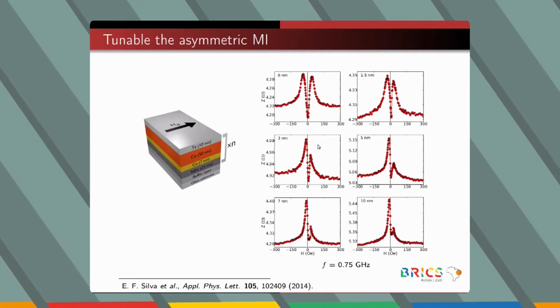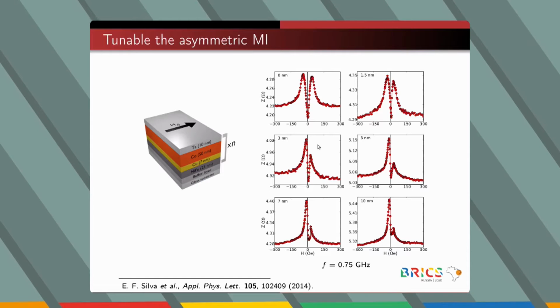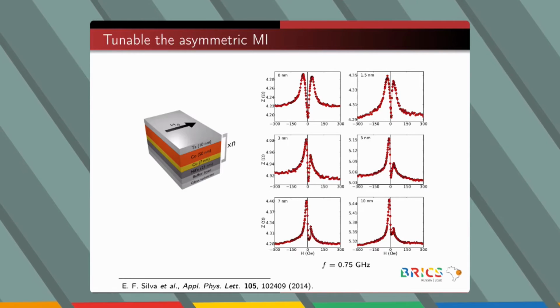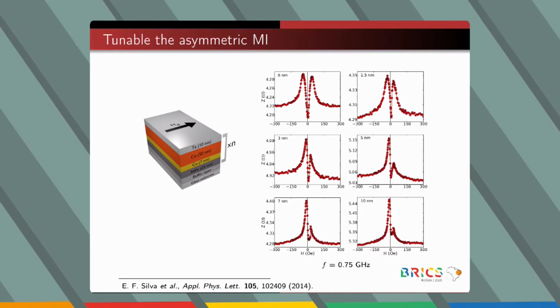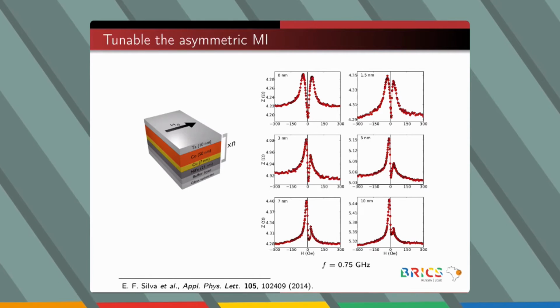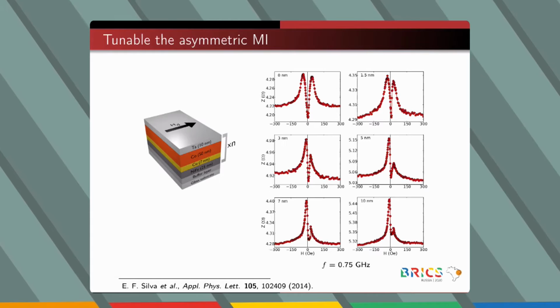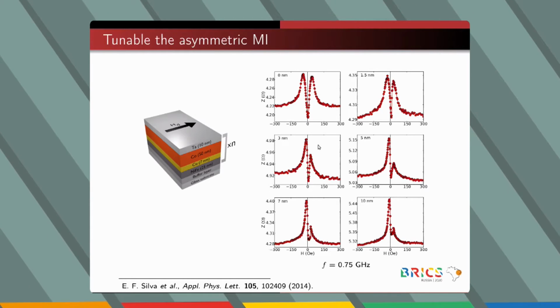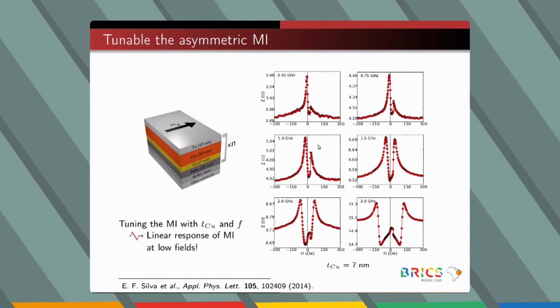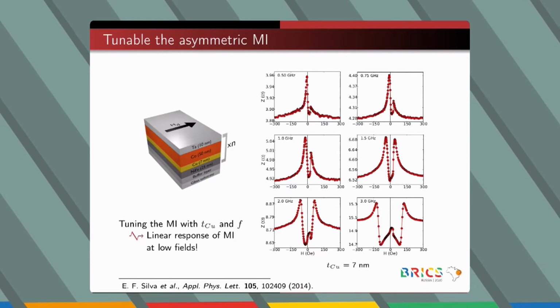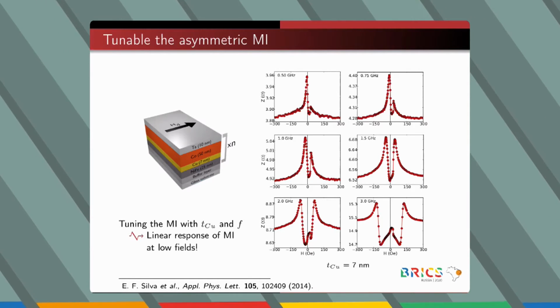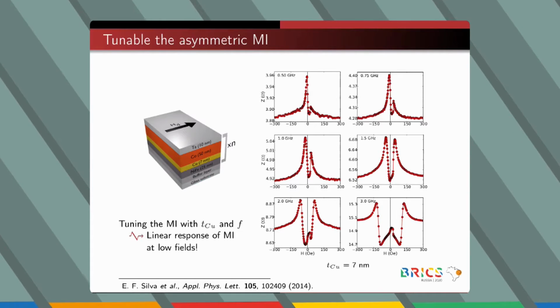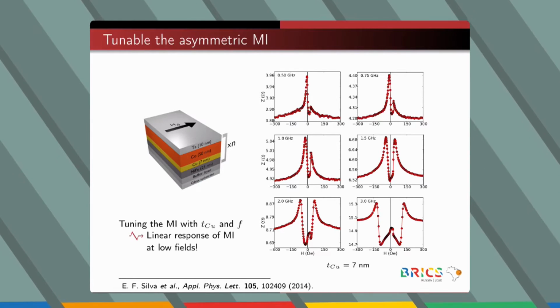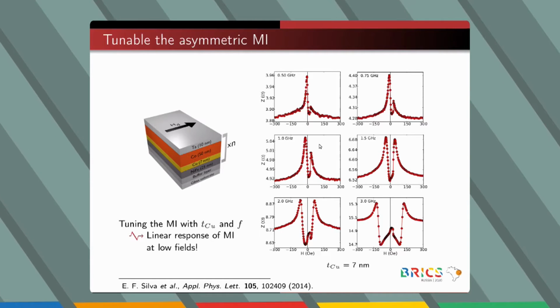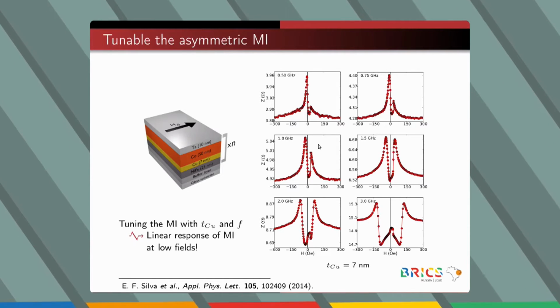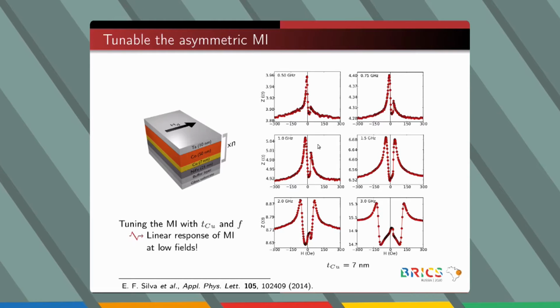tri-layers consisting of two ferromagnetic layers with different magnetic features separated by a non-magnetic material. In this case, by varying the thickness of the spacer, we verify an evolution of the magnetoimpedance curves. We can also change the shape of the curves, keeping the thickness of the spacer constant, and varying the frequency of the experiment. In this case, we obtained asymmetric magnetoimpedance curves. In a sense, you can turn on the linear response of the magnetoimpedance at low fields by changing the sample